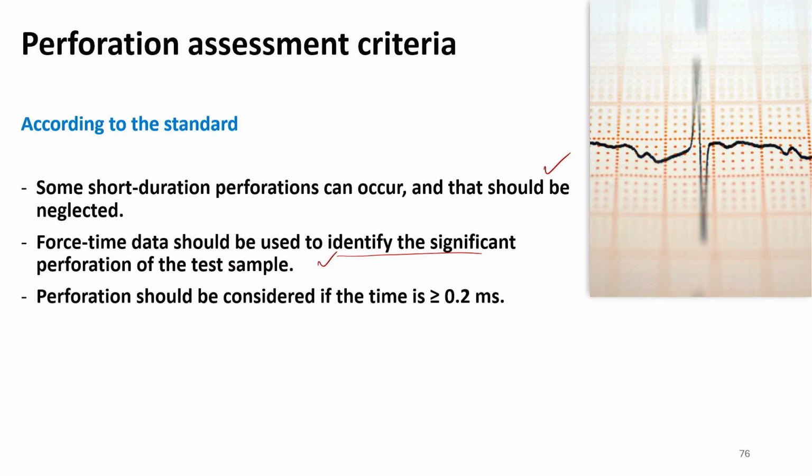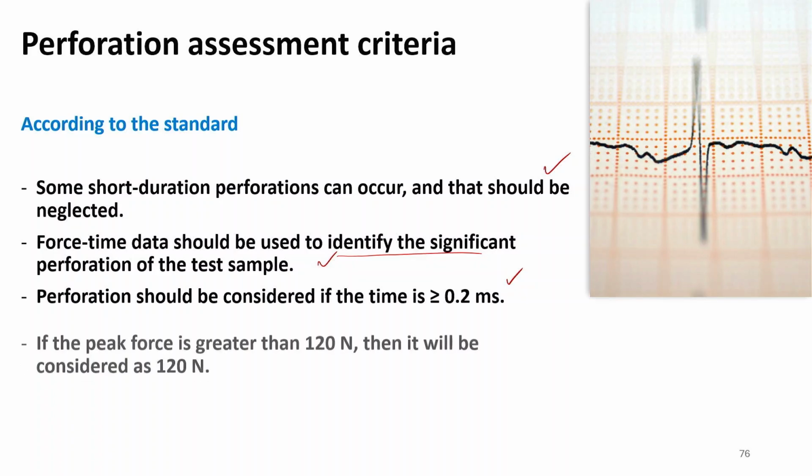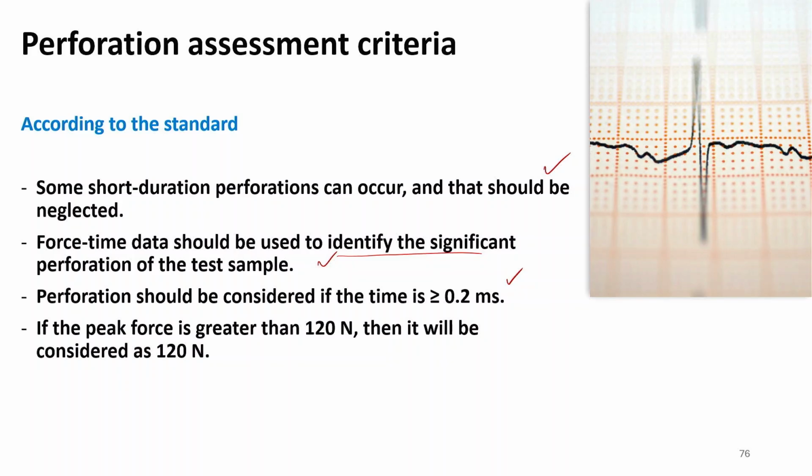Perforation should be considered if the time is more than 0.2 millisecond; otherwise it will be neglected because it is a short duration perforation. If the peak force is greater than 120 Newton, then it will be considered as 120 Newton.